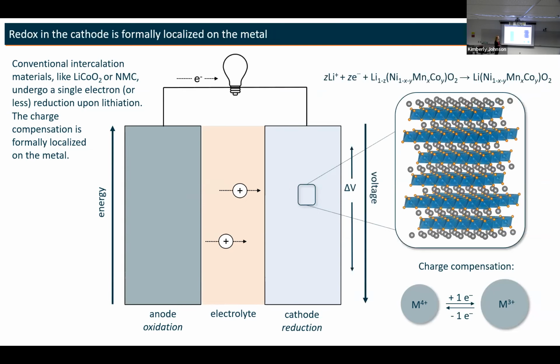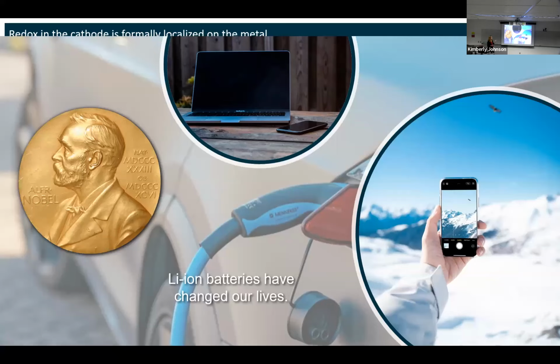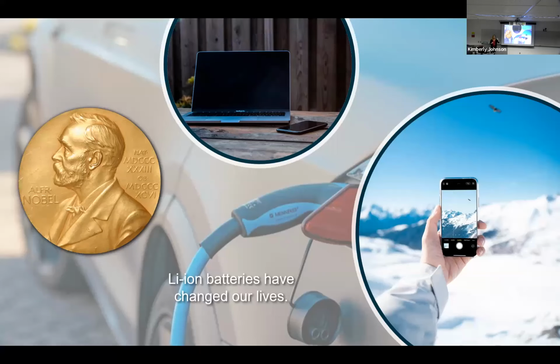So this is an example of a metal oxide that's used. This is lithium cobalt oxide just for simplicity. But now commercially, if you take cobalt and substitute manganese and nickel, you can get much higher capacities to yield these so-called NMC materials, so nickel, manganese, cobalt, and these are the commercialized type materials. So I just want to show you what those look like here. But the operation principle is the same. Lithium shuttles in and out between these van der Waals gaps, and you get reduction oxidation of those transition metals. Okay, so lithium-ion batteries have revolutionized our lives, enabled portable electronics, EVs, and they've also really been enabled by the chemistry, which was recognized by the Nobel Prize in 2019.